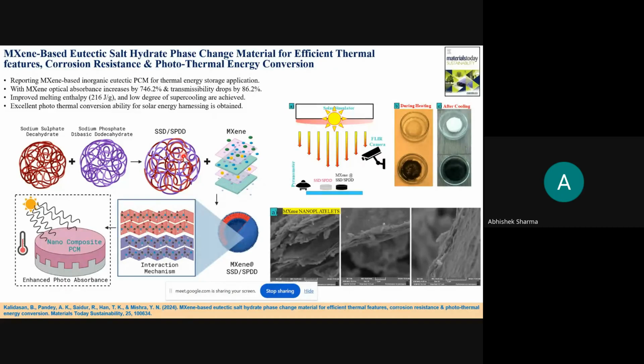This material has excellent electrical conductivity, but the thermal conductivity is not that high. And we tested it with one of the eutectic salt hydrate phase change materials. However, this is for one particular eutectic salt hydrate phase change material, so it can be further investigated for other phase change materials. What happens with the MXene?